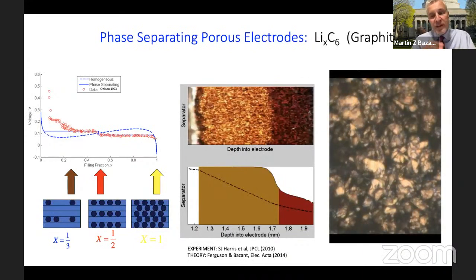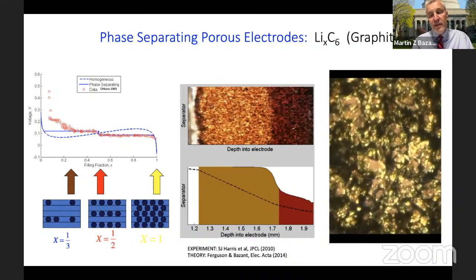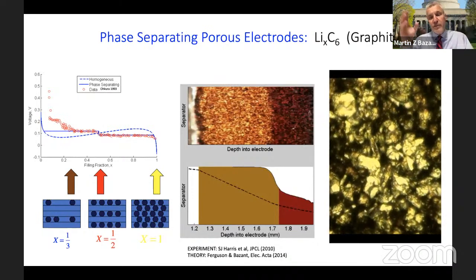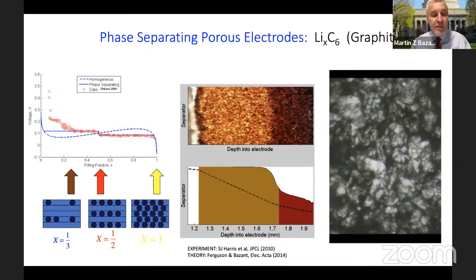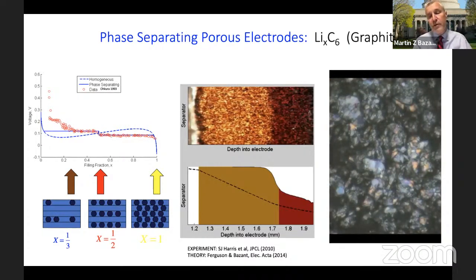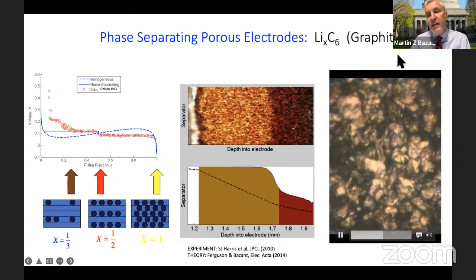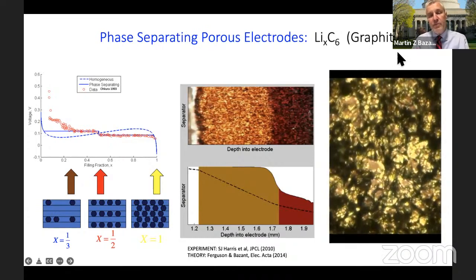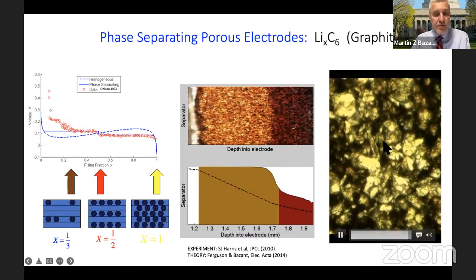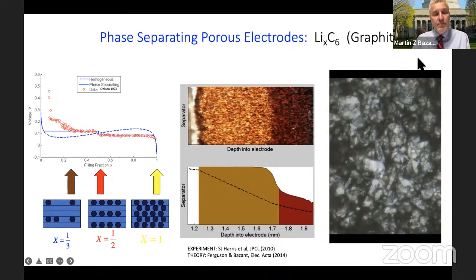So what you notice, it's not a smooth diffusive process. It's very much like I showed you before. You have these stochastic non-uniform phase transitions that are driven by the electrochemical reaction. And you do need the kinds of models that I've been showing you to be able to explain this behavior.